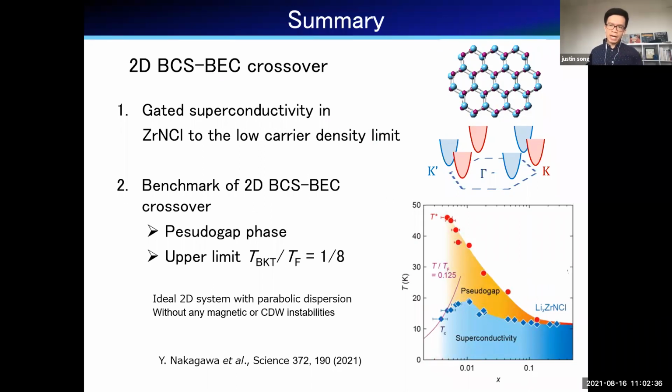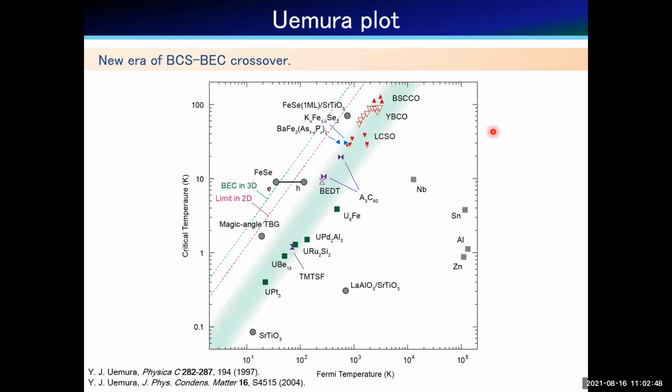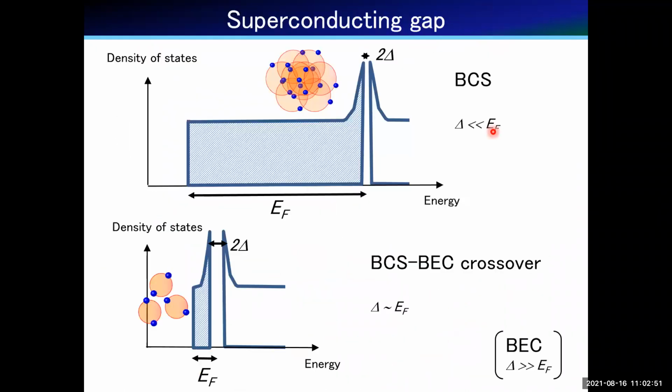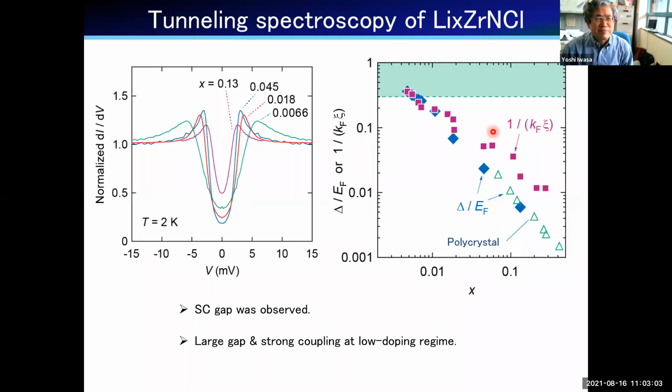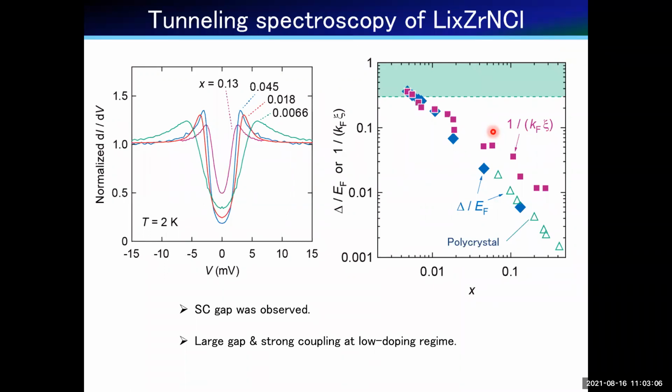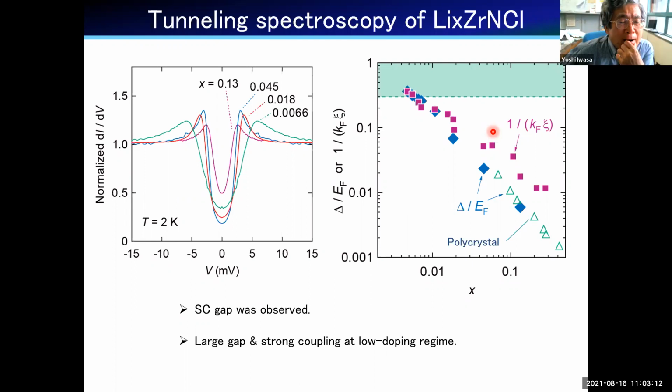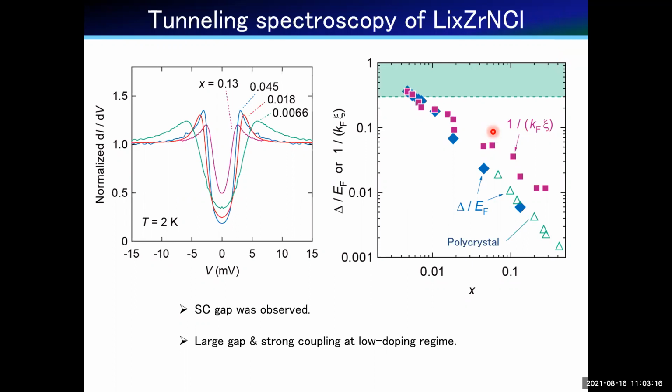So Alexander had a question, and then we'll go to Weipo. Thank you for the very interesting talk. Could you show your tunneling spectroscopy data again at low carrier densities? At your lowest carrier densities here, your zero bias conductance is enhanced, and your coherence peaks are very wide, which is indicative of an enhanced Dynes parameter. So a short quasi-particle lifetime and increased scattering. Do you think this could be indicative of some type of emergent heterogeneity in your samples?